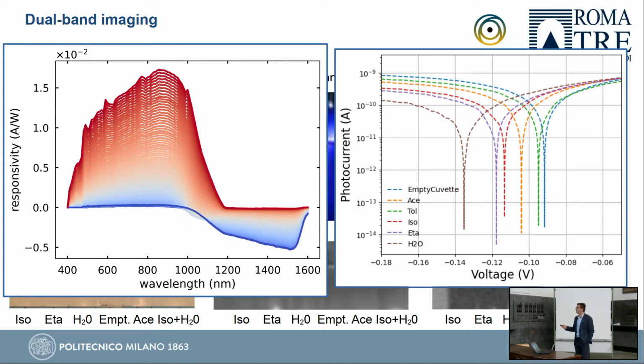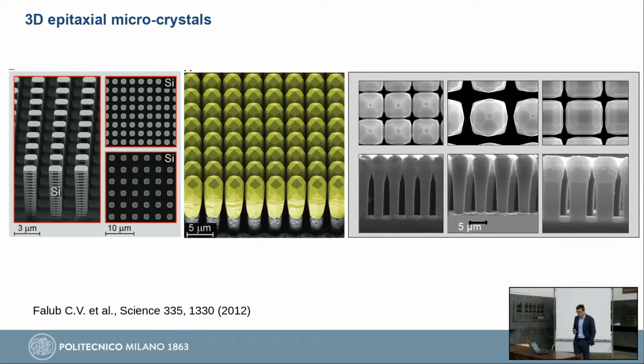So we see that all this structure, the absorption, is limited to the band gap of germanium, the direct band gap of germanium, which is around 1550 nanometer. It would be actually nice to go farther in the infrared. And again, we can exploit another possibility offered by semiconductors, which is micro and nano structuring, to do this and move farther in the infrared. So what we did a few years ago was actually changing the substrate. So we don't grow anymore on a flat silicon substrate that you buy from a supplier. But before performing the growth, you can do this deep etching. So you can carve these pillars, which are typically 10 microns tall and a few micrometers wide. And you can do this over a very large area. And again, this is something that is done very easily with silicon. With other materials, it would be very difficult to obtain.